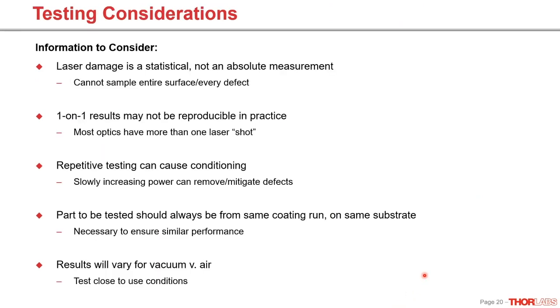As far as testing considerations, there are a few things to keep in mind here. For one, laser damage is a statistical, not necessarily an absolute measurement. Even if you're testing some portion of the surface, you can't sample the entire surface and you can't sample every defect. So you will occasionally see failure at or below the damage threshold. That's something to bear in mind. One-on-one results may not be reproducible in practice.